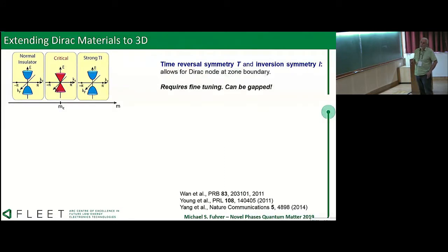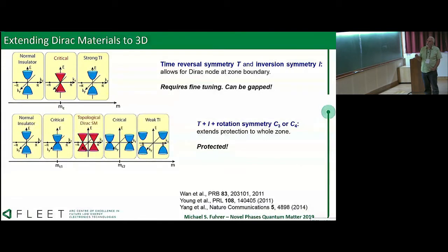This happens, for example, in the bismuth antimony alloy series as a function of antimony concentration. You can tune through this point. This does require fine tuning. And these points can interact, and then so they can, in principle, become gapped. And so it's not the best way to do it. But it turns out if you add an additional symmetry, so in addition to the time reversal and inversion symmetry, if you have some rotational symmetry in your system, you can actually preserve this topological Dirac semimetal over a range of parameter space. And so you can have these Dirac cones in 3D.